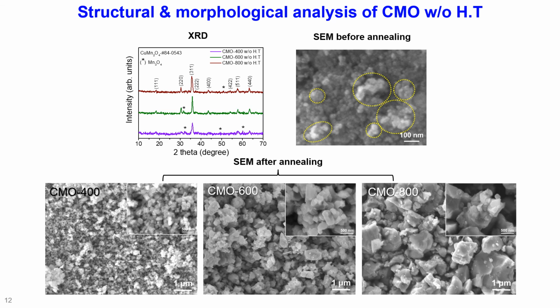Then the SEM before annealing shows a similar kind of aggregated morphology. Then after annealing, there is no polyhedra morphology of these CMO nanoparticles, which shows that not only EG but also the hydrothermal treatment influences to produce the faceted CMO nanopolyhedra morphology.